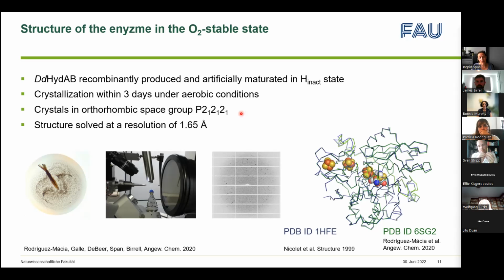The protein crystallized in the orthorhombic space group P212121, and we were able to solve the structure at a resolution of 1.65 angstrom. This is one of the prettiest crystals that we obtained. This is the setup for X-ray diffraction experiments, and this is how a typical diffraction pattern looks. Nowadays, the detectors are so powerful that it's really hard to see the diffraction pattern at all, but luckily the software recognizes the spots and is able to calculate the structure.